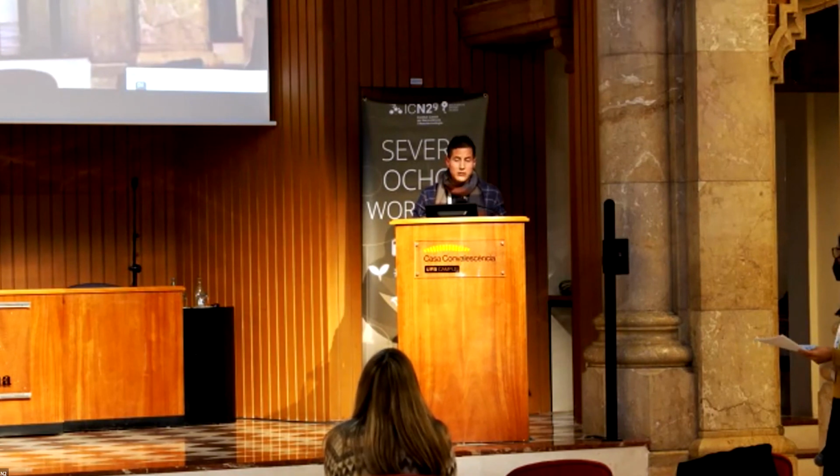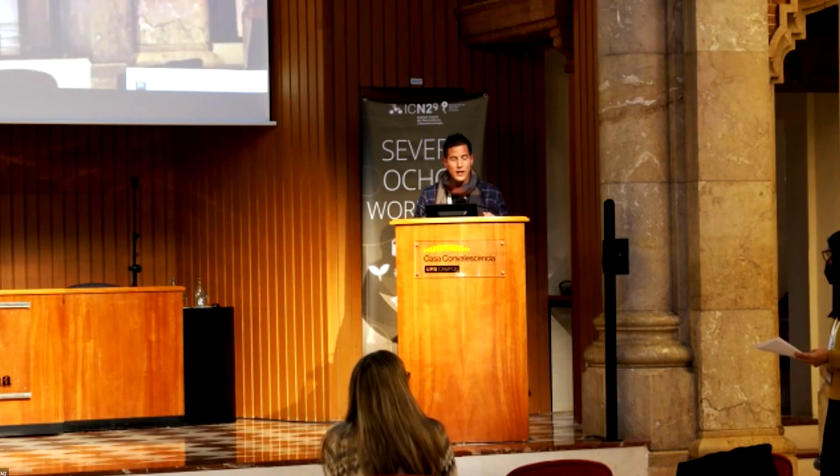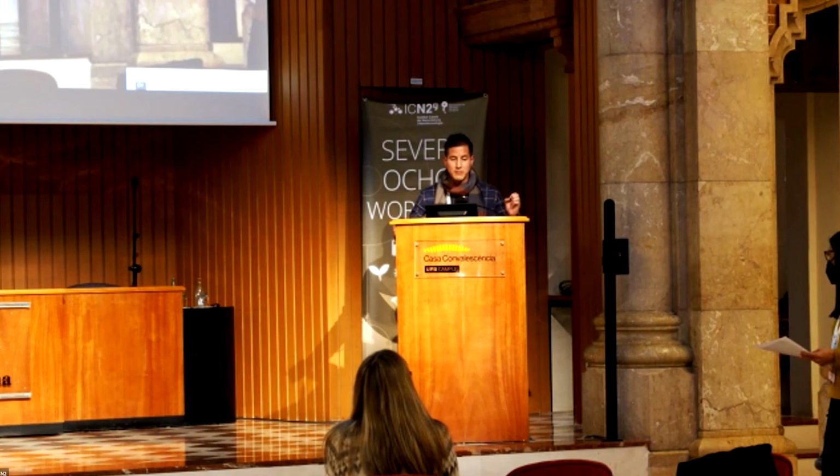The polymerization reaction is a tricky one because it uses radicals and temperature, and this can dissolve the silica. So the nucleation of the polymer on top of the silica and the multi-contrast agent needs to be fast. I had a really hard time controlling the perfect timing before dissolving the silica and growing the polymer. That's why I put the external layer of 20 nanometers, because it was really complicated.